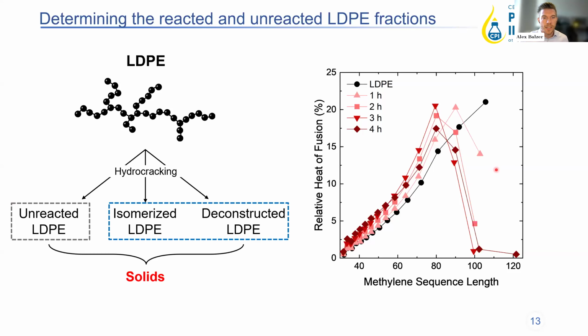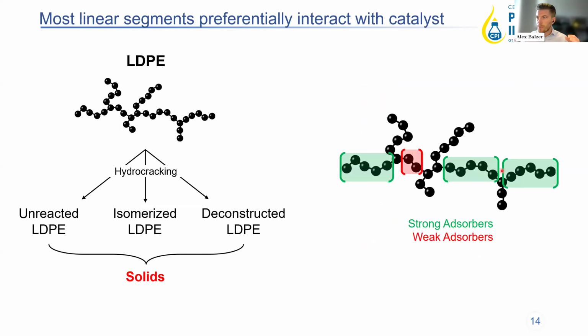And so basically, what that's telling us is that when we look at the LDPE chain, the most linear portions, so the furthest spacing in between branches, act as the strongest absorbers to the catalyst. They preferentially interact with this catalyst, while the areas that have a lot of branches nearby are very sterically hindered. They don't want to absorb to the catalyst as much. And so that's how we can start to understand how the polymer architecture, where the branches exist, how many of them exist, affects your catalyst activity and kinetics.